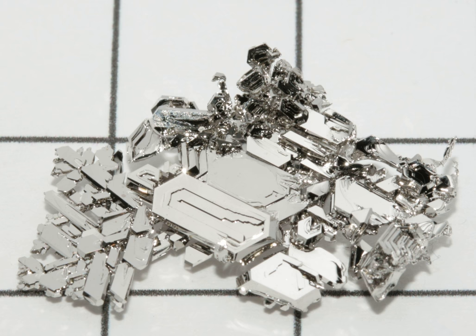Platinum is one of the least reactive metals. It has remarkable resistance to corrosion, even at high temperatures, and is therefore considered a noble metal. Consequently, platinum is often found chemically uncombined as native platinum. Because it occurs naturally in the alluvial sands of various rivers, it was first used by pre-Columbian South American natives to produce artifacts. It was referenced in European writings as early as the 16th century, but it was not until Antonio de Ulloa published a report on a new metal of Colombian origin in 1748 that it began to be investigated by scientists.